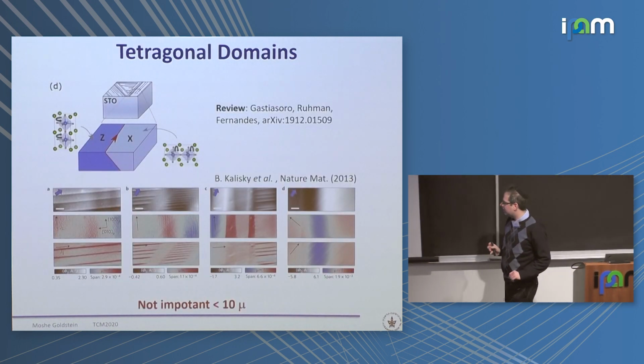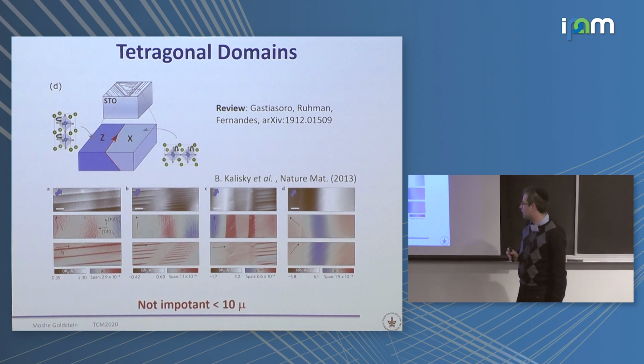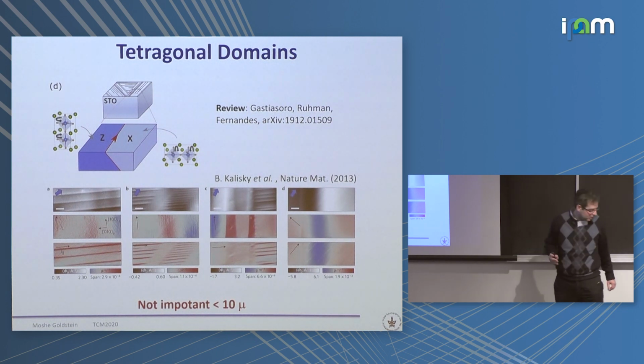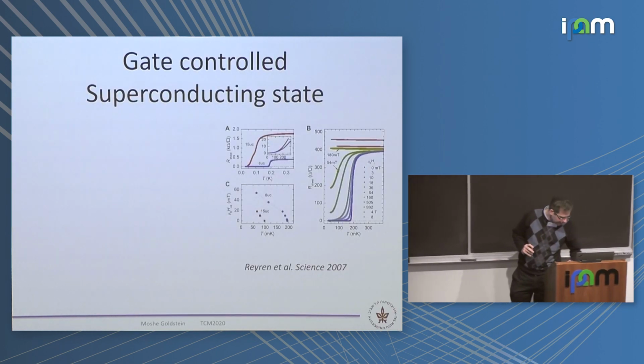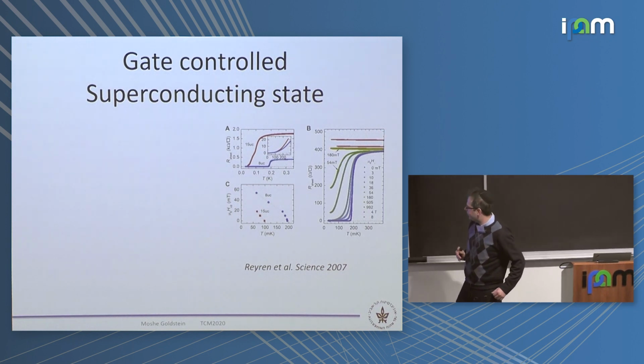Another thing that I'm going to forget about is that I told you that there is this tetragonal distortion below 105K, and actually you can have different domains where this tetragonal distortion can be along X, Y, or Z. And if you have a big sample, and again this is a scanning probe, you see that actually conduction is enhanced along the domain walls and maybe even superconductivity, but the samples I'm going to tell you about are going to be smaller than that, basically smaller than the typical domain, and we have evidence that they're basically single domains, so domain wall physics is interesting but not going to be important to us.